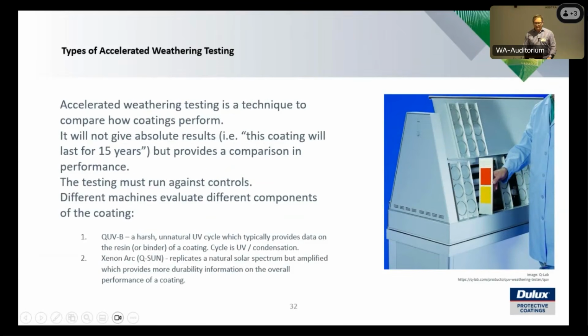So the techniques or the tests that were undertaken, third-party testing I'll add, were two tests. The QUVB, which really is a fairly harsh test, and it really gets down and tests the impact that the resin will have over the testing process. And the Xenon Arc, or the QSUN as I'll refer to it in this test, more simulates a day-night scenario or real-world conditions as well, and then we'll pick up on pigment performance from that as well.